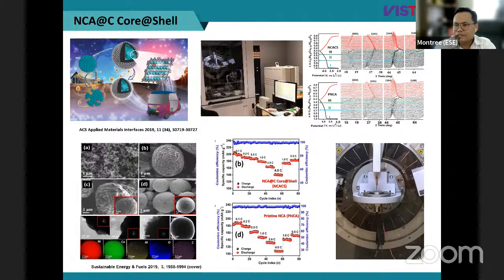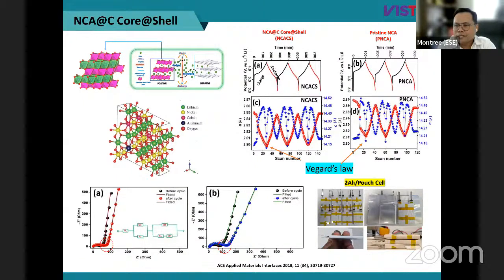We have X-ray diffraction to look at the structure of the material when we do charging, discharging. Yeah, for example, maybe I cannot go to details in terms of too much scientific. We do testing, like in operando X-ray diffraction, what is going on in the structure, see the lattice, right? If we look at the unit cell of the material, we need to go there at that level, in angstrom level, we see the expansion, even there, 10% in graphite, or contraction in the cathode when we pull out the lithium.